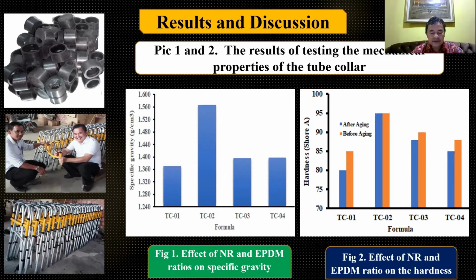Figure 2, effect of the EPDM ratio on the hardness. Hardness describes the level of material hardness per unit cubic centimeter. Hardness test data from 4 samples of vulcanized rubber before aging and after aging. For TC02, the value is higher, 95, than the other formulas. Theoretically, the hardness value is directly proportional to the specific gravity. When the specific gravity value increases, the hardness value will also increase.